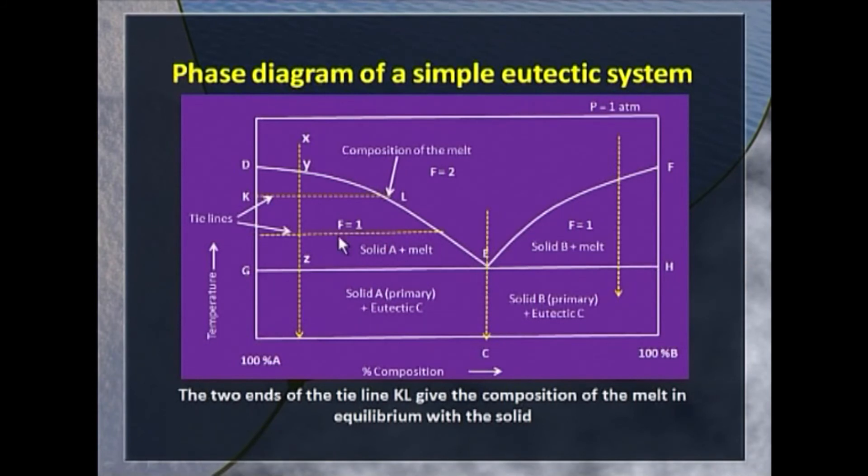If you are interested in separating pure solid A or pure solid B, you have to stop cooling just above the eutectic temperature. But another point you can see here: if the overall composition is to the left of C, it is possible to get solid A. If you are to the right of it, you can get only solid B. You will not be able to separate both solid A and solid B in the pure state. It will be very interesting to study the behavior of a system in which the composition corresponds to point C here. C is the eutectic composition. If you heat it and take it to the molten state and then cool it, as you reach point E, the system becomes a three-phase system. Because the two lines intersect, solid A and solid B crystallize out. Three-phase system means number of degrees of freedom is zero. System becomes invariant. Cooling is resisted till one of the phases disappears. In this case, the molten phase disappears and then you go below the solidus curve.